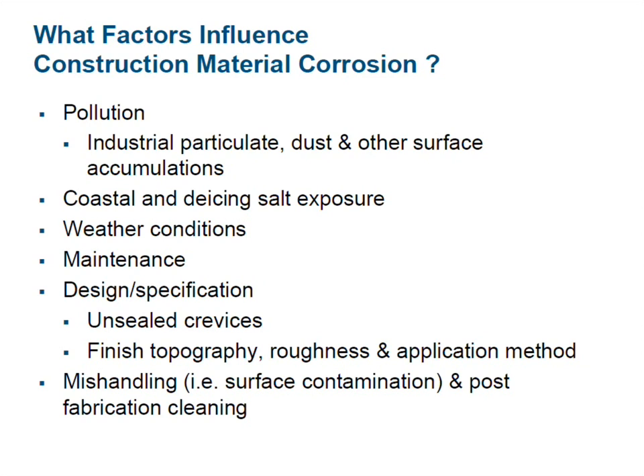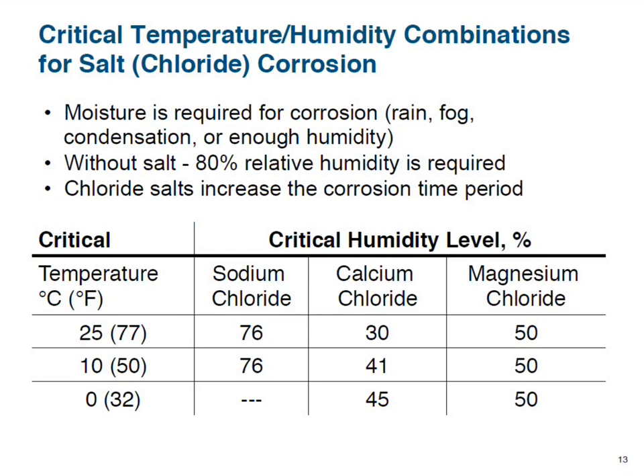If you get regular heavy rain and you have a structure that's fully exposed like the arch, then you get natural rain cleaning. And at the top, with wind levels, we probably get power washing levels of rain cleaning, as happens at the top of the Chrysler Building, because that was measured as well. Will there be maintenance? And are there aspects of the design that might cause corrosion problems, like unsealed crevices? And then the type of finish that you have also makes a big difference. Mishandling, as was mentioned, occurred a little bit during installation, can also cause some surface contamination and damage.